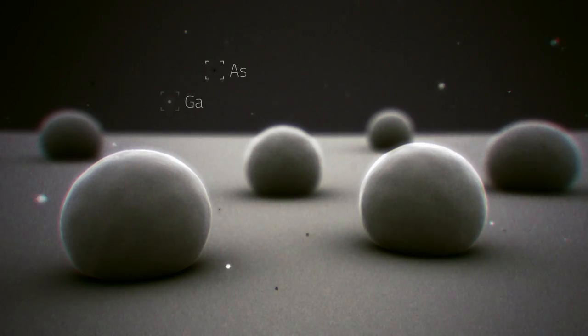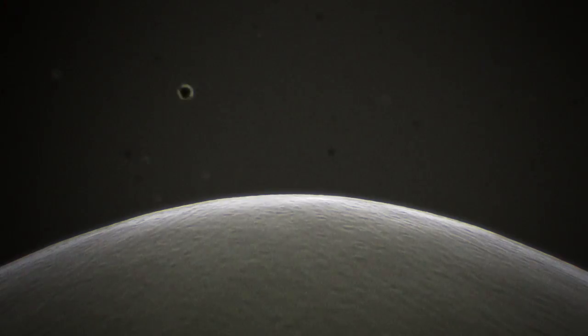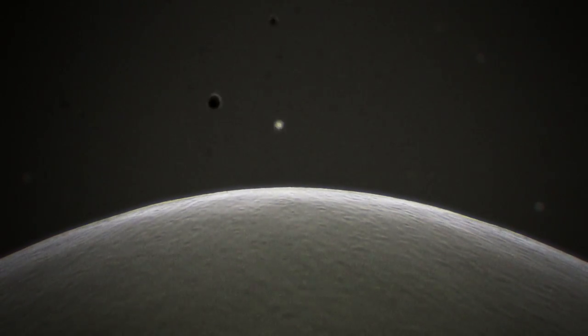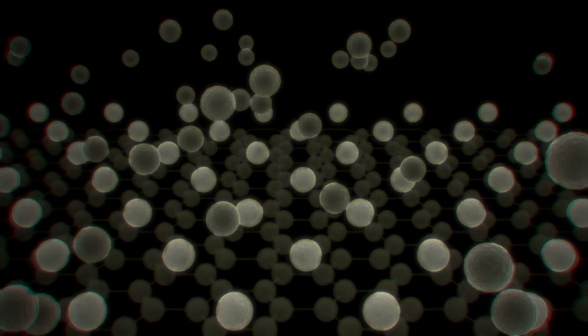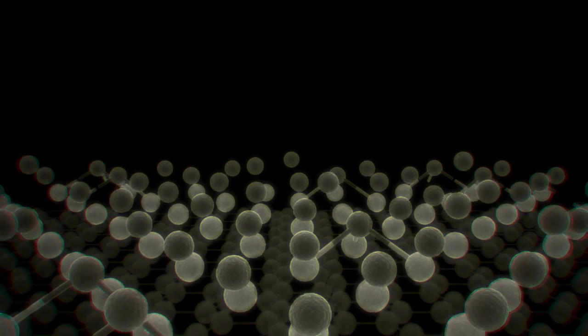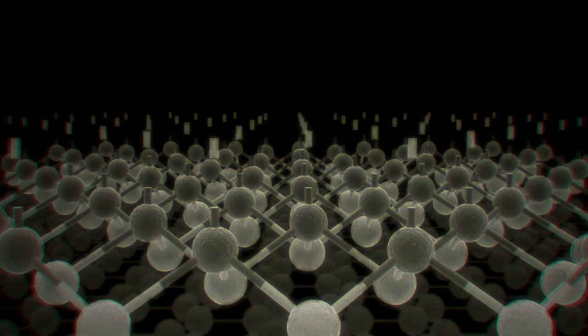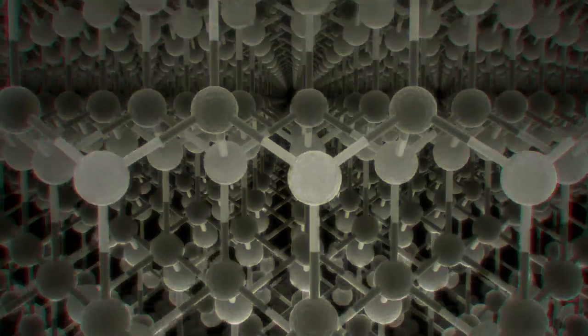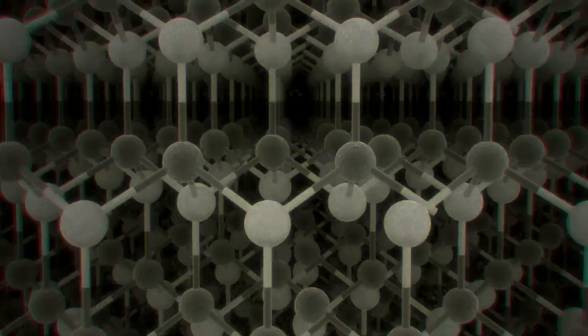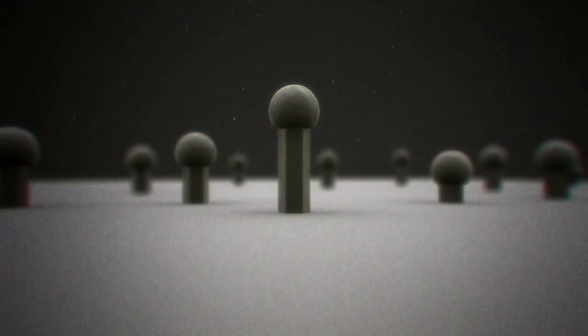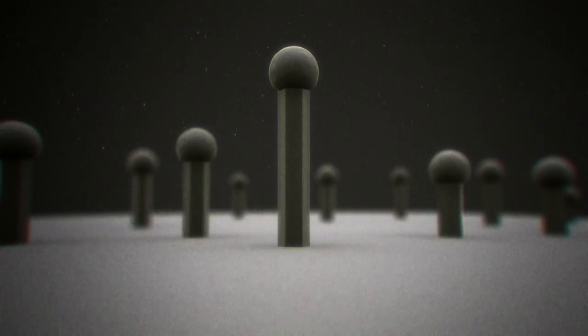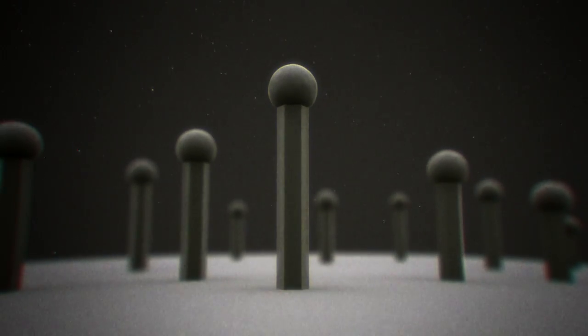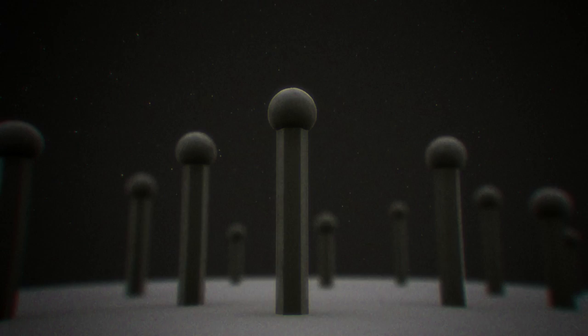Now gallium and arsenic atoms hit and enter the gallium droplet. Down at the bottom, inside the gallium droplet, the gallium and arsenic atoms chemically bind together and form a gallium arsenide crystal, layer by layer. In this way, vertical gallium arsenide nanowires with a hexagonal cross-section grow longer and longer under the gallium droplet. It only takes a few minutes of growth before they reach the desired length of 1 micrometer.